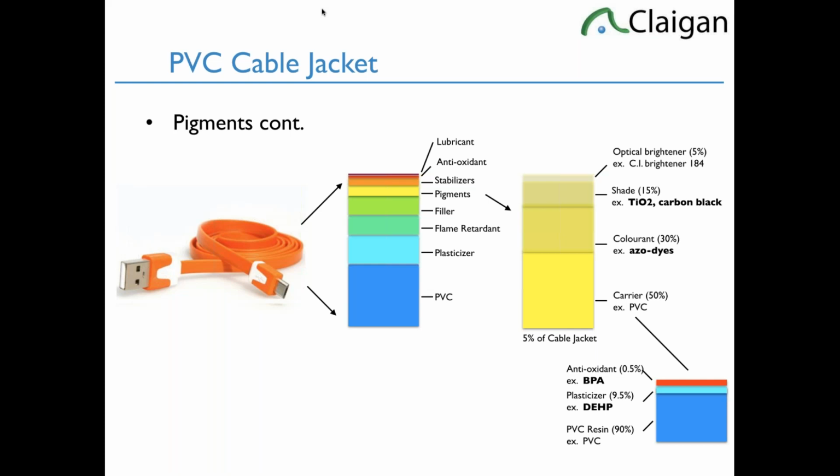So when we see BPA in PVC, if it's around 2,000 ppm, it's from the plasticizer. If it's around 500 ppm, it's from the colorant. If it's around 10 ppm, it's the antioxidant for the base PVC, or at least partially. And so this is not uncommon, where you have DEHP getting into the PVC from the colorant.